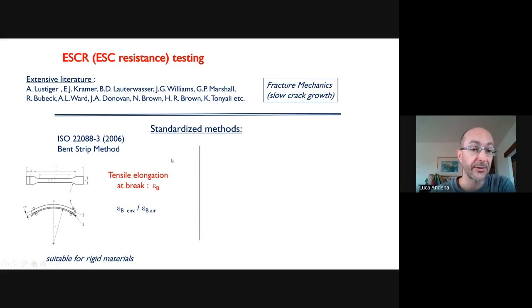The first one is the bent strip method, which is generally used for rigid materials like amorphous polymers, like polystyrene seen before. And the idea here is that I take a tensile sample and put it on a template with an applied deformation, and then it's immersed within the medium. So you have the simultaneous presence of the mechanical stress due to bending and the environment, and then you test the sample and compare the strain at break with the value of the strain at break that you obtain on a sample which has not been immersed. And of course, the reduction in the strain at break will tell you how much the material is sensitive to ESC.